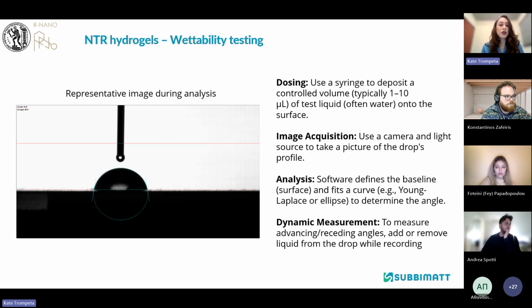Then we need to capture the profile of this drop on specific time intervals. Most of the cases we have the time that the droplet is attached on the surface. So this is the 0 point. In other cases, we could also have extra time intervals when we need to study a dynamic phenomenon. Then there is the image acquisition, where we use the camera and light source to take the picture of the droplet's profile, and the analysis.